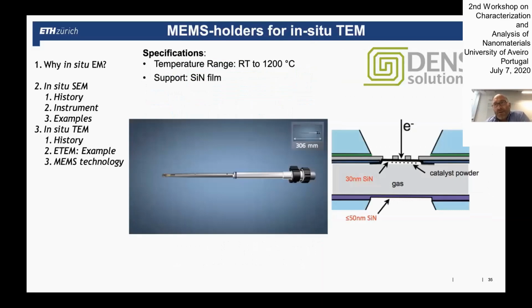These were now two examples of this environmental microscope that has these differential pumping apertures. And if you have a normal microscope without such differential pumping apertures, then you can actually buy commercial holders for in-situ TEM. This is basically a TEM sample holder that has in the front, where you normally mount your normal TEM grid, a small nanoreactor. Here's a scheme of how that looks. So you have in the microscope the electron beam, and where normally your sample is, you have this nanoreactor.